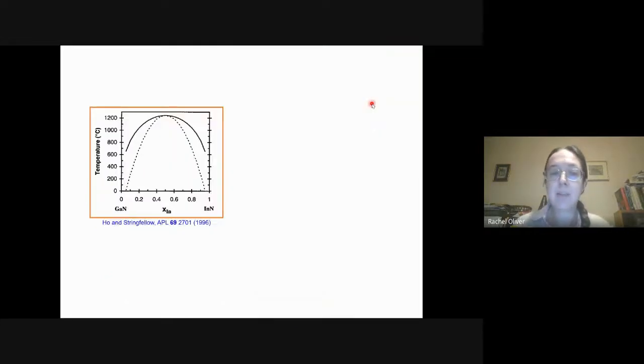Well, one thing a metallurgist would do would be to look at the phase diagram to figure out whether the thermodynamics of the material is expected to lead to it being all broken up into these high indium content regions. This is an early phase diagram for gallium nitride and indium nitride. The composition of the material is along the x-axis and the temperature is along the y-axis. And underneath this solid line here, what we'd expect is to see the material splitting up into gallium nitride and indium nitride rich regions. And that would include the temperature for growth of indium gallium nitride in LEDs.